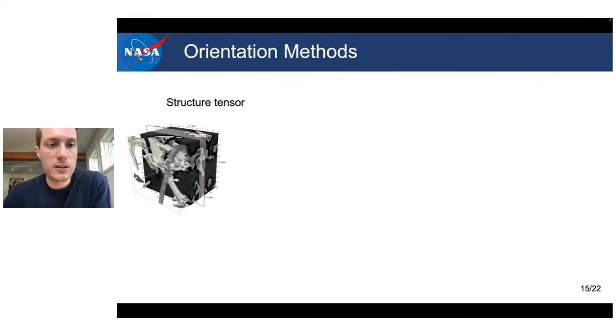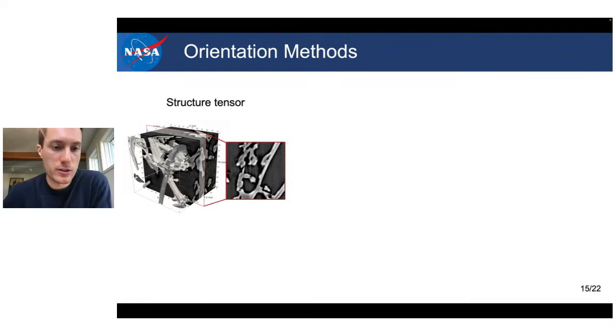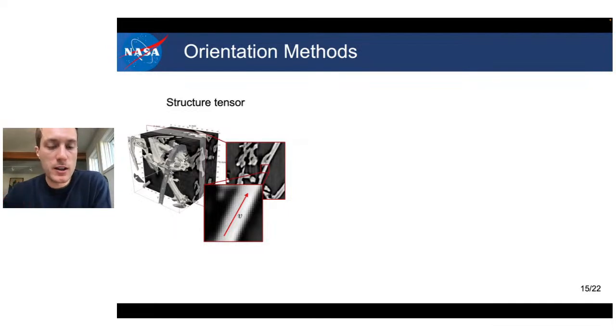So starting from the orientation methods, there are 3 different functions that we've implemented. The first one we call a structure tensor, and it's based on an image processing technique called the structure tensor, which looks directly at the grayscale values of your tomographic domains, and it picks out by applying different Gaussian blurs and derivative of Gaussian filters, and doing an eigenvalue analysis on these filters, we can pick out the direction along which the gradient of these grayscales changes the least. And this turns out to be a very good estimate of the local orientation of our fibers.